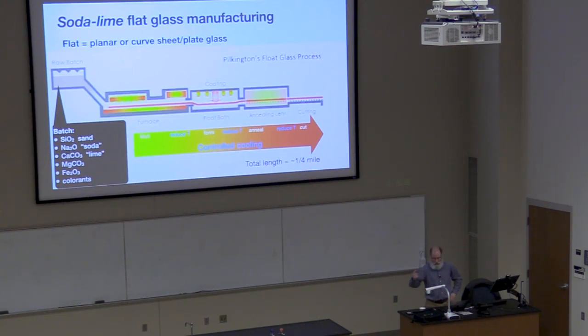So you've got to get all the bubbles out, and once you get the glass fully mixed, then you've got to get it to the right temperature. And at this point right here, the glass flows over a spout, meaning this molten glass, it's kind of like molasses or honey, flows onto a bath of molten tin. So the glass flows and floats on the tin, and it spreads out. And I'll show a picture of that in a minute.